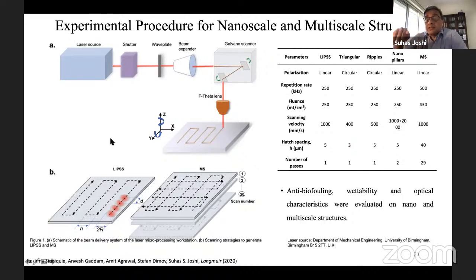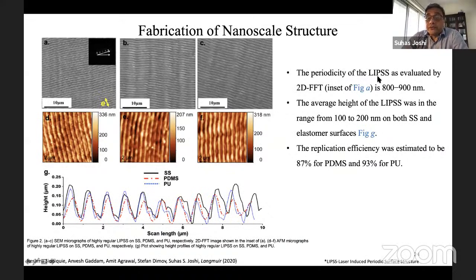The third type of structure is generated by scanning strategies. You have several scanning strategies, and you perform those scans multiple times, 1, 2, 3, 4 times, or 20 times, and then you generate a variety of structures. So here laser-induced periodic structures are created, generally called LIPSS. You can see that nanoscopic structures are created, and the reddish or brownish pictures are pictures of the replicated structures on PDMS and PU. So these polymeric replications of the nanoscopic structures will help you to develop those structures on polymeric substrates, and these polymeric substrates have a large number of properties. So these textures developed can act as a mold, and then these structures can be replicated on the polymeric surfaces.